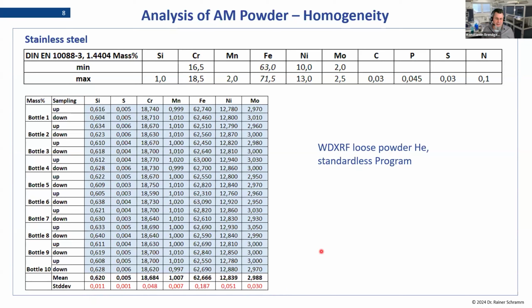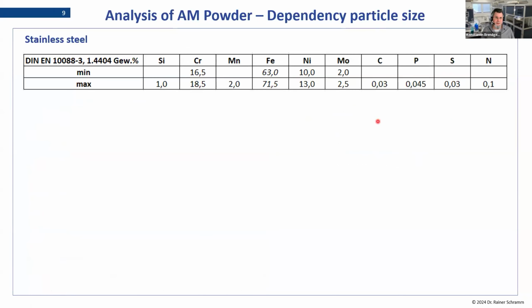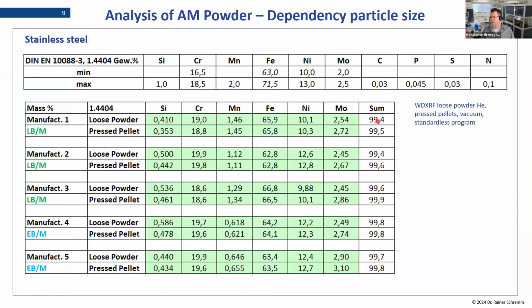So unlike a natural product where you have a lot more different effects, this one is a homogeneous sample and a very defined particle size, and that explains why even with very little effort, just taking loose powder and measuring, we get a very good reproducibility and a very good homogeneity in the different bottles of one charge. And this is for the one sample, the test of homogeneity, pretty good homogeneity in the end. That was the result. We then checked the loose powder and compared it to a pressed pellet.